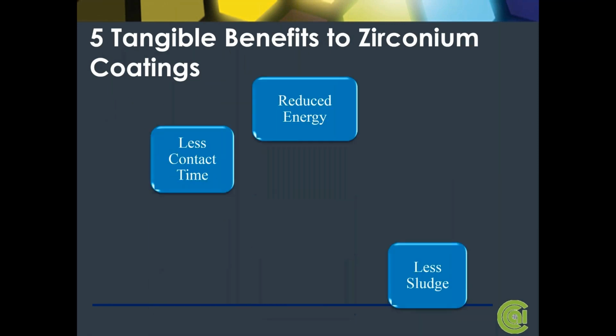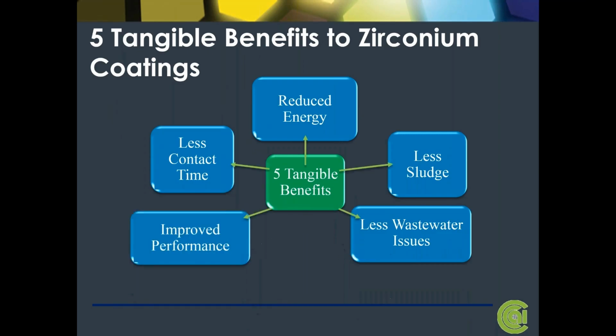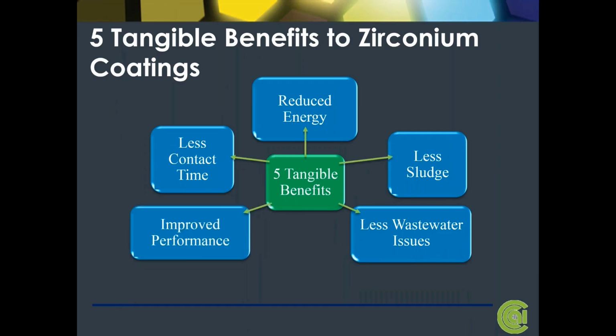Here are the five tangible benefits that we know for using zirconium: reduction in energy, reduced sludge, less wastewater, improved performance, and less contact time. If you can reduce your energy, you're going to lower your heating costs and your energy costs. Like I said, you can get a good crystal structure at room temperature with zirconium, where you have to heat the iron phosphate.